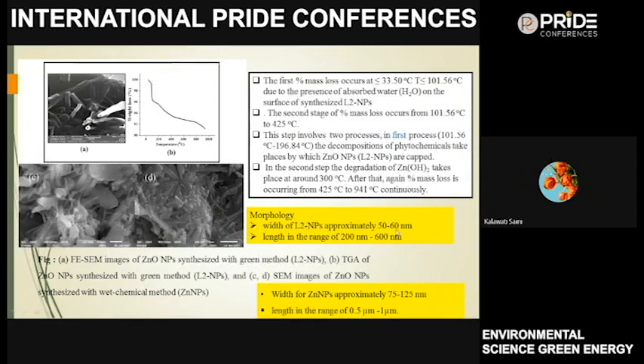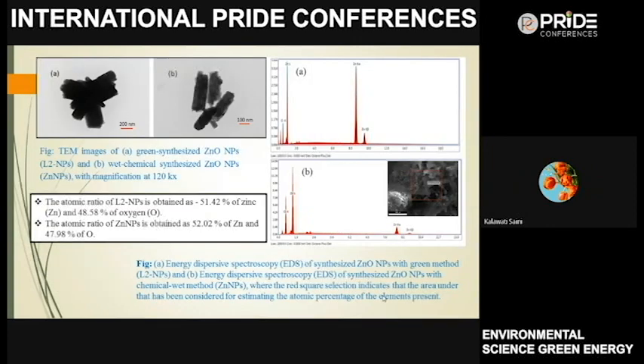The size of L2 nanoparticles is 50 to 60 nanometer in width and 200 nanometer to 600 nanometer in length. For the chemical wet method, the width is 75 to 125 nanometer and the length ranges from 0.5 micrometer to 1 micrometer. It means with the chemical wet method, the particles have higher dimensions than the green one. These are the TEM images. The first one is regarding green synthesis, the second one regarding the wet chemical method. It means in the green method, the particles are in a more agglomerated state.